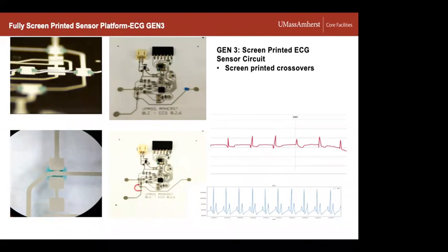So this is some work we did with our partners, United Technologies, and again, showed that we can screen print. The green here, if you look at the images on the left, the green is a dielectric. So we can actually align and print that over the conductor. And then we come in with a second conductor and we print over that bridge. And so now you're connecting two pads in the opposing or orthogonal direction without shorting to the lead that you're crossing over. And so that allows us to go to 2 dimensions in our layout and further can enhance the density of the circuit design.